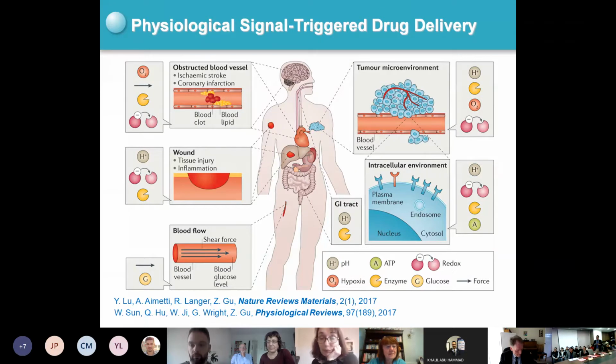For example, the tumor microenvironment is a bit acidic. So you can design acid-sensitive materials or formulations to encapsulate the drug inside, and then deliver such formulations to the tumor microenvironment or even a subcellular environment. Under such acidic environments, the formulations can be easily degraded, dissociated, swollen, or shrunk to promote the release of the drug to enhance the healing effects. For diabetes treatment, the increased blood sugar level can be leveraged to promote the release of insulin to quickly maintain the blood sugar level in a normal range. Also, you can identify different biological signals as a trigger to promote the release of the drug.